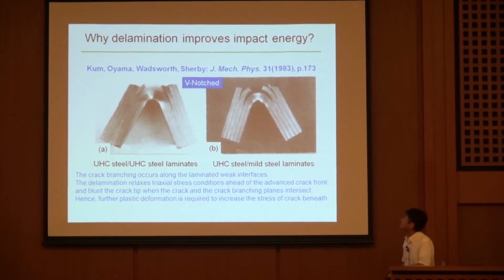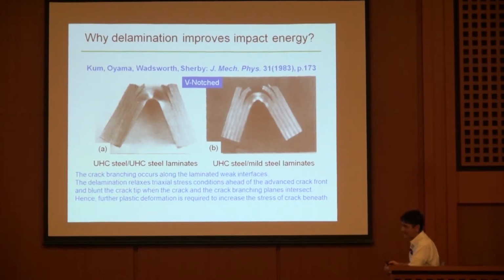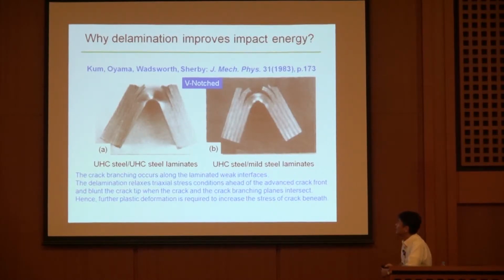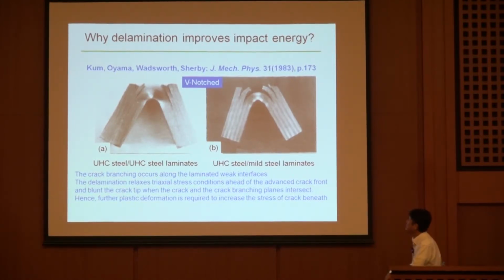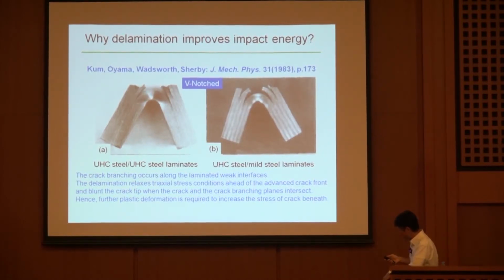You may ask why delamination improves impact energy. It was proposed by a research group of Professor Sherby in 1983 with laminated steel sheets like this. You can see the delamination fracture like this. Clearly, the crack branching occurs along the laminated weak interfaces. The delamination relaxes triaxial stress conditions ahead of the advancing crack front and blunts the crack tip when the crack and the crack branching plane intersect. Then further plastic deformation is required to increase the stress at the crack tip. This is one of the reasons why delamination improves the impact energy.